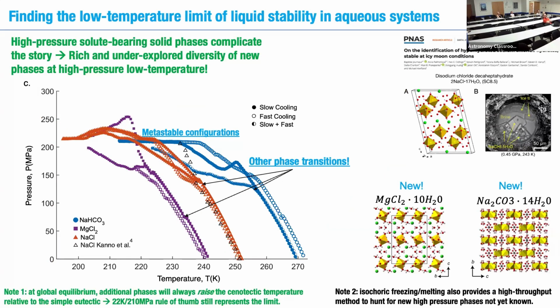Now, what about when they aren't simple eutectic salt systems? Well, it turns out one of the big stories to me in the last 5 years of aqueous thermodynamics at low temperature, high pressure, is that we had just no idea how many fascinating, crazy phases of interesting solute-bearing hydrated solids exist at low temperature, high pressure, right? So these curves now, this is what you see when you start to run into other intermediate phases en route to your cenotectic. So these are non-simple eutectics. Every time you see a kink in the PT curve, there's some kind of phase volume difference happening, some step change that represents a phase change, right?